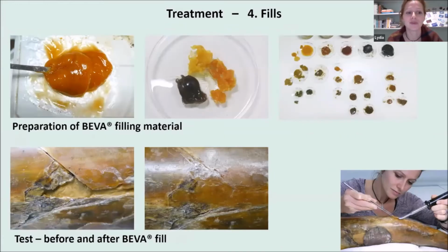In the end, I moved away from Paraloid, epoxy resin and Beva gel and followed the advice of my colleague to use Beva film. Free of solvents, the dry and transparent Beva film eliminated the risk of shrinkage that comes with the gel. As the material is a thermoplast, I could melt the film on a hot plate and mix in different dry pigments ranging from yellow ochre to raw umber to create colored discs. I then mixed various ratios of these together to create a wide range of hues in brown and ochre. In a small area of loss, I tested the material and found that I can achieve with it the desired opacity and sheen.